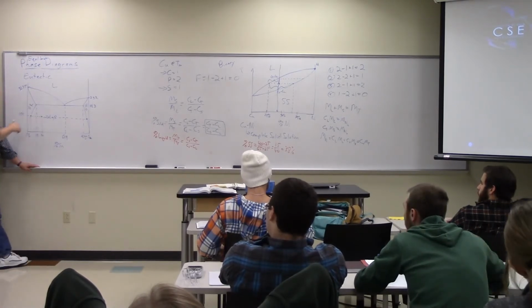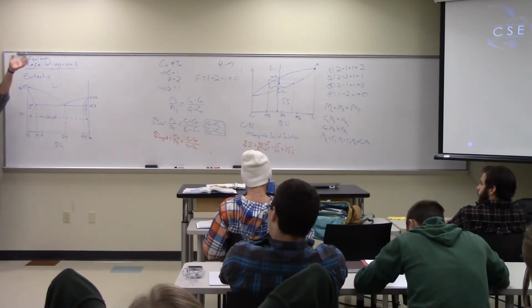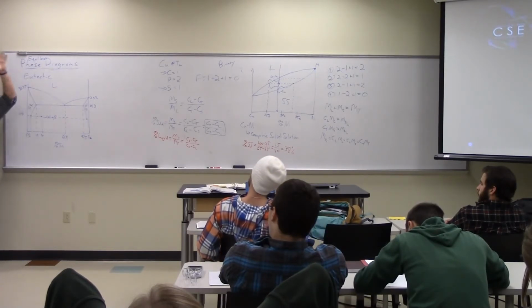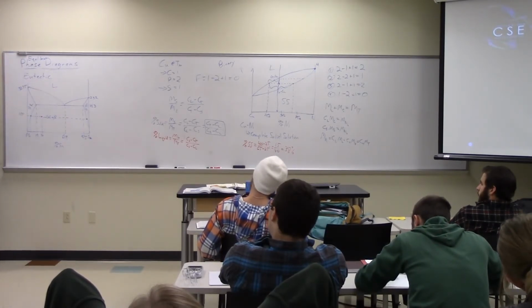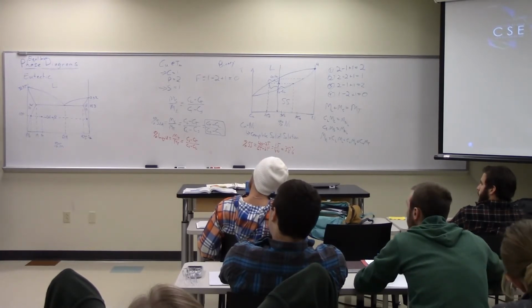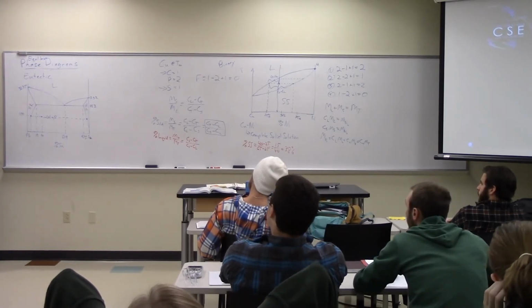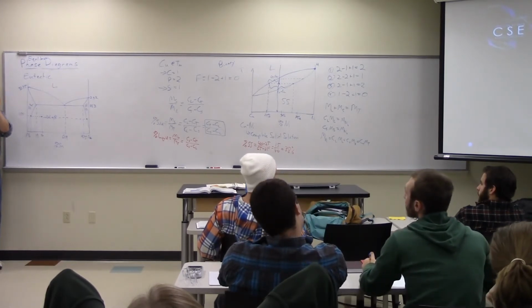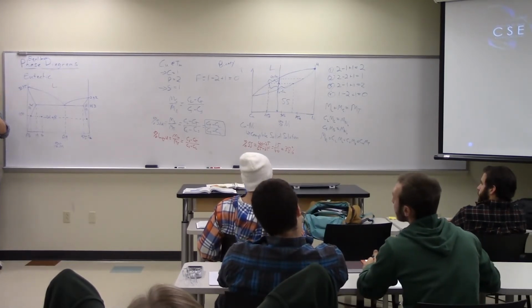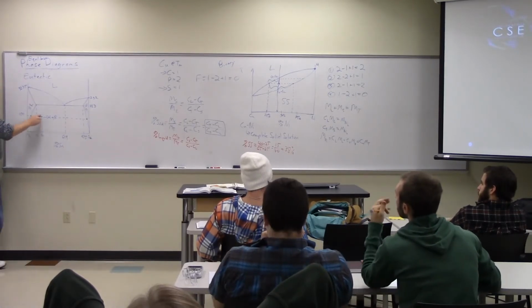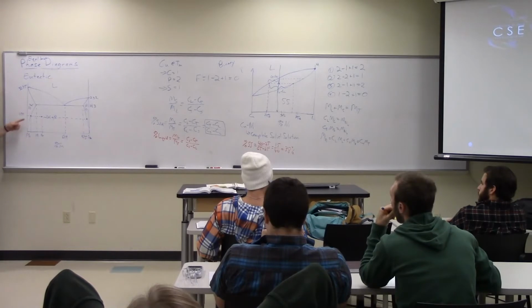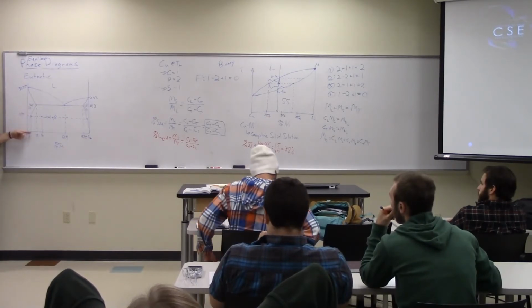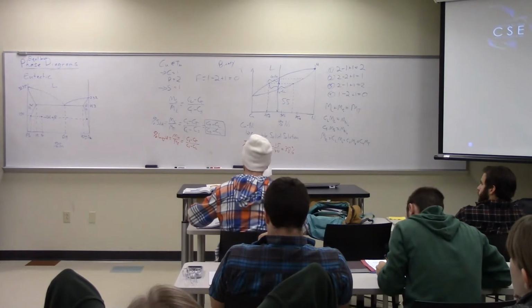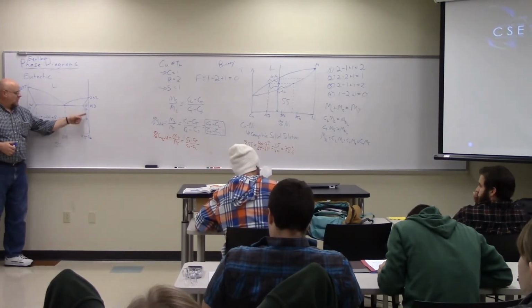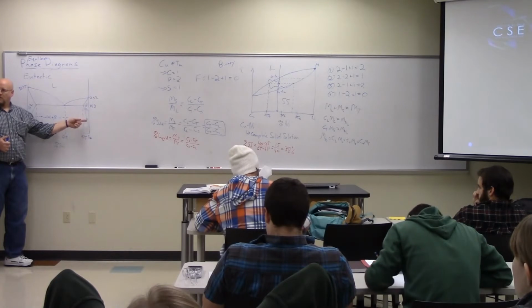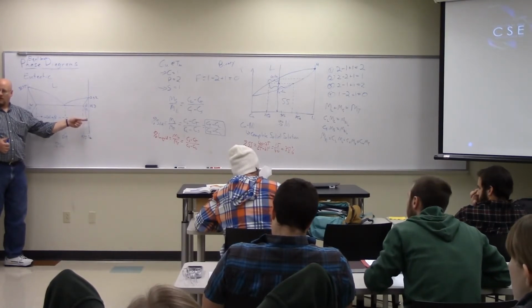But if I go to 30% out here, that's too much. I can't do that with uniform tin atoms scattered throughout the lead. What will happen is the tin will agglomerate together and form chunks of tin-rich region, which we call beta, leaving behind the lead-rich region, which we call alpha. At this particular composition and temperature, that alpha has a composition of roughly 8%. That lead-rich region has 8% tin in it. And the tin-rich region has this percent, which might be 99% tin. So there's only 1% lead dissolved inside the beta.